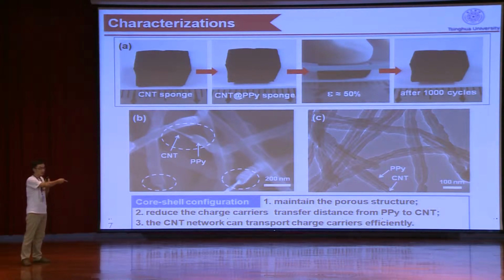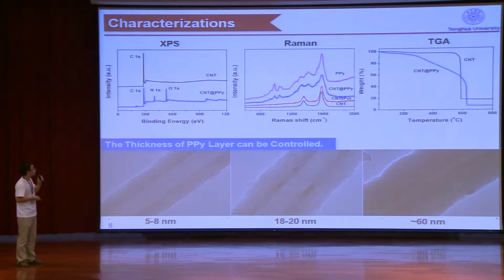And the SEM and TEM images also show well-controlled PPY deposition. A uniform PPY layer wrapped each individual carbon nanotube and forms the core-shell configuration. It can maintain the porous structure and reduce the charge carrier transfer distance, and also the CNT network can transport the charge carriers efficiently. And other characterizations, XPS, Raman, TGA, also confirm the successful deposition of PPY. And more important, the thickness of the PPY layer can be well controlled in our method. By controlling the PY solution concentration and the absorption period, we can control the thickness range from 5 to 60 nanometers.